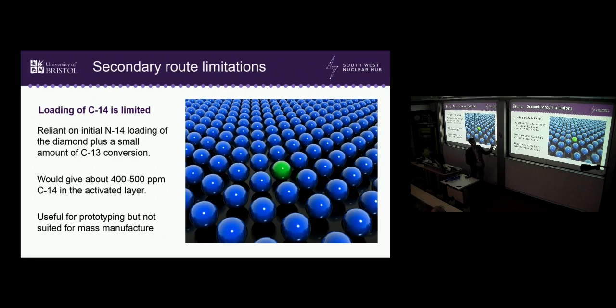And it's relatively small loading, so some of the nitrogen that you would have will convert, your carbon-13 will convert, and if you do put deuterium in, that will convert to tritium, so you have different isotopes. If you were to run in a test reactor which has fast neutrons, then you'll actually generate another beta-emitting isotope called beryllium-10, and that's a very powerful beta emitter. So depending on how flexible your test reactor is, you can grow in different radioisotopes. So you can have different flavors of diamond battery made this route.